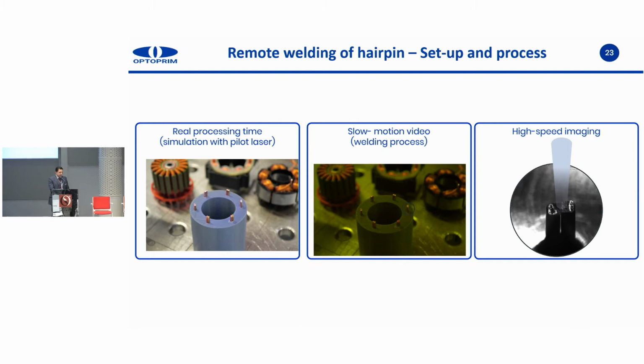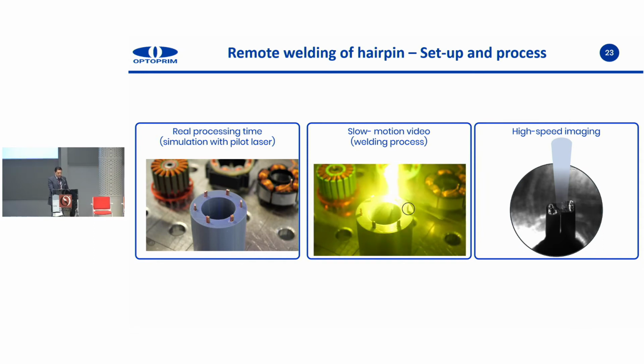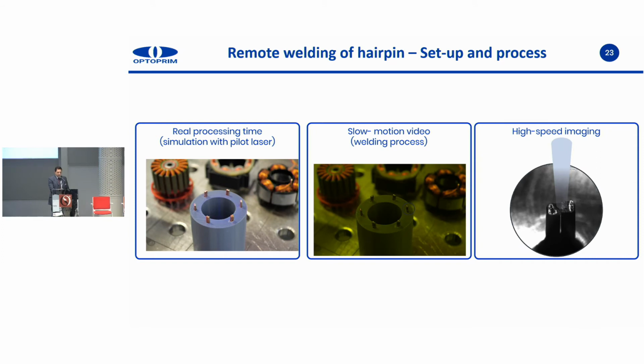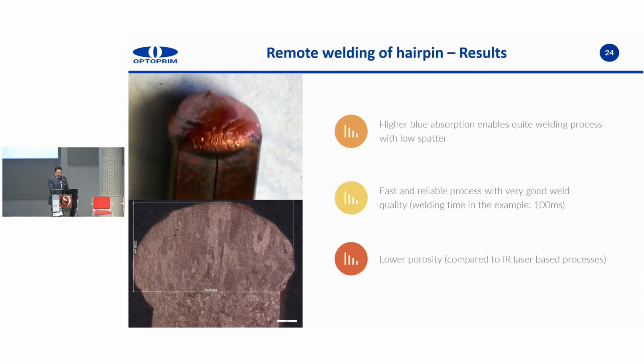Here we show the result. The first video just shows the process at normal speed with a visible laser. The second one shows the real process with the blue laser in slow motion. Most important is the last one, where you see in high-speed imaging the very calm process due to the high absorption of the copper already at room temperature. There is, in the video, no spatter at all, and the melting pool is very calm and stable. We inspected the sample, and again, due to the high absorption of the blue, we have a fast, reliable process with very good weld quality, and through the cross-section you can see that the porosity is very minimal.